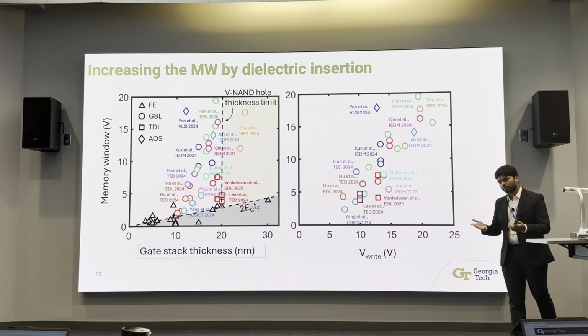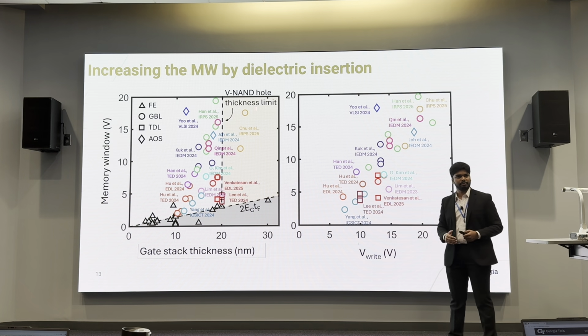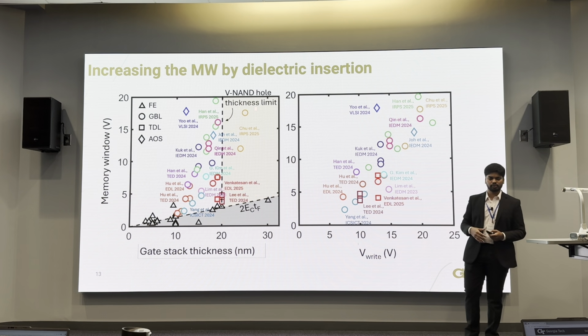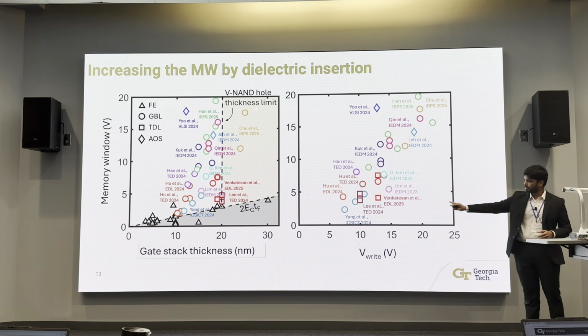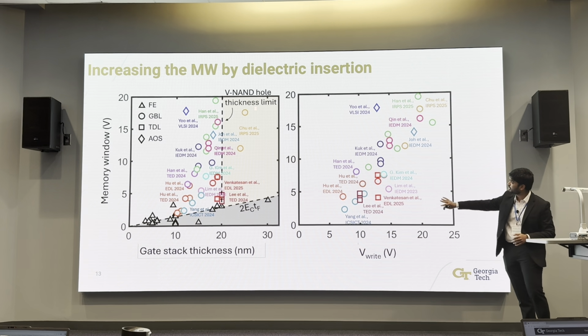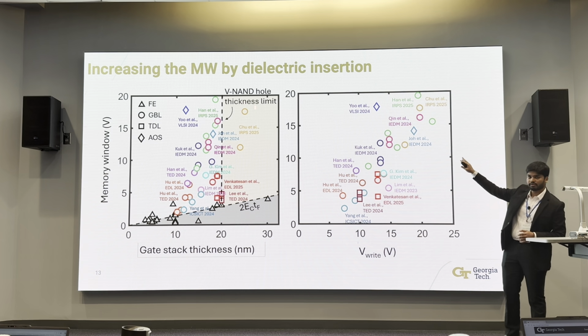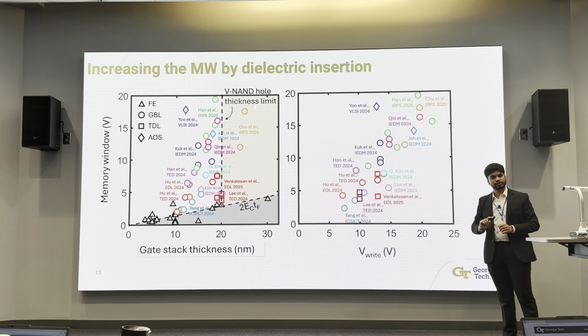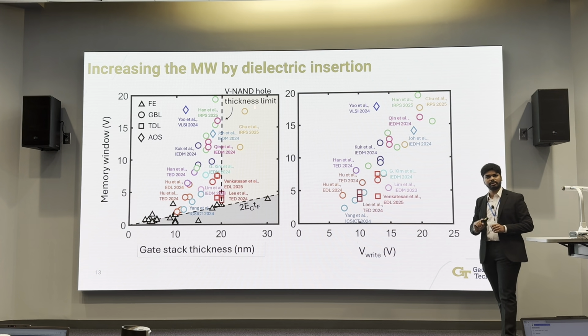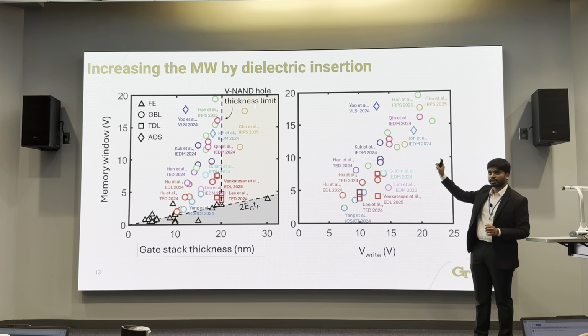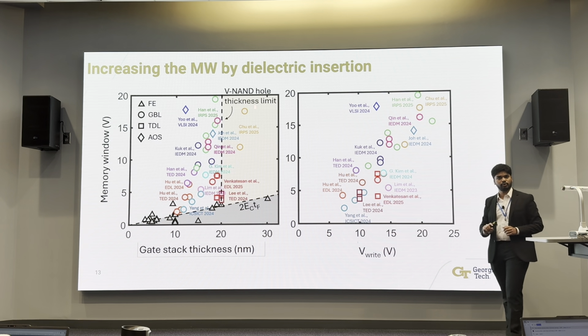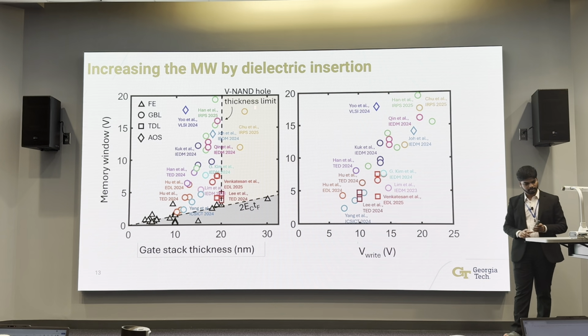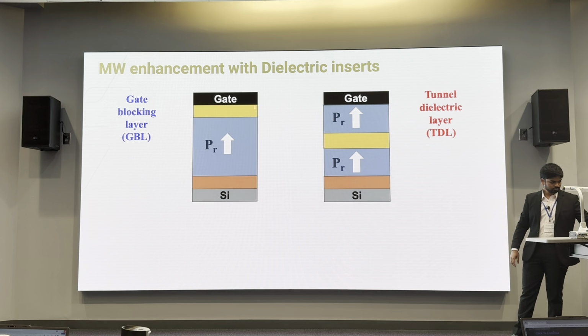So you might say, what use is a 20 volt memory window if your write voltage is 50 volts? But here is a benchmark showing that memory window and write voltage scale roughly 1:1, and we even have results where amorphous oxide semiconductors were used as a channel material, and Samsung demonstrated close to 17 volt memory window with a 13 volt write voltage.